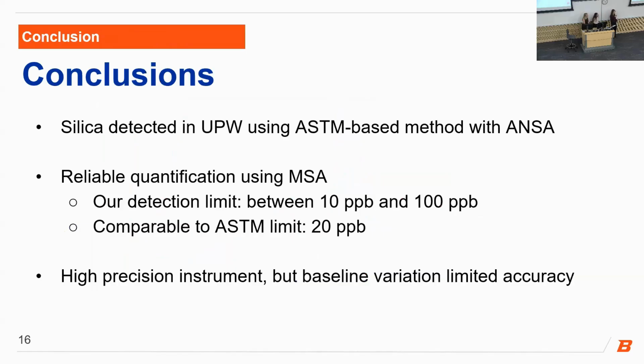So in conclusion, we're able to detect silica using the ASTM-based method using an ascorbic acid reducing agent down to 100 parts per billion. Our method detection limit is likely somewhere between 10 and 100 parts per billion, which is comparable to that of the ASTM's documented method detection limit of 20 parts per billion. While instrument precision was pretty high, our baseline error significantly reduced accuracy and therefore impacted our method detection limit.